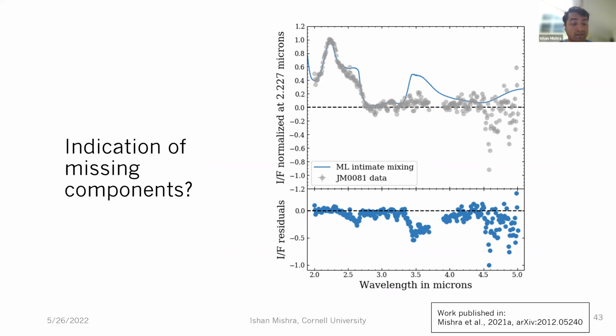But on the other hand, the absorption coefficients or the refractive indices that we need to model all those species do not exist in the literature beyond 3 microns. And actually, beyond 2.5 microns. So both of these regions of mismatch, we could not really go ahead and model. But hopefully, when that lab data comes along, I'll get to revisit these spectra and try to understand what